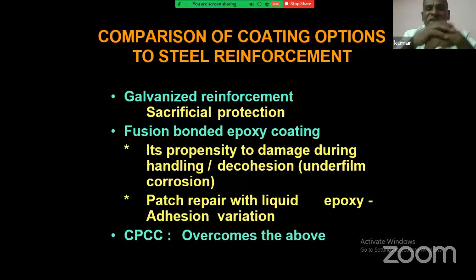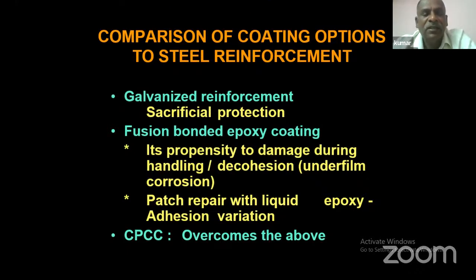Comparison of coating options for steel reinforcement. One is galvanized steel. They have experience; they have tried it in various locations, and it gives sacrificial protection. People are using it, especially in the UK, where one of the bridges completely used galvanized reinforcement, and they were successful. Next, currently in India and elsewhere, fusion bonded epoxy coating systems have been used. The fusion bonded epoxy coating is completely epoxy. It is a highly organic coating. It's a barrier type of coating. You can simply apply it on the steel surface and use it.